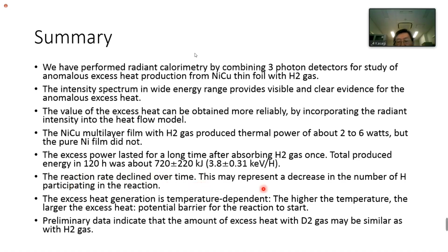This may represent a decrease in the number of hydrogen atoms participating in the reaction. The excess heat generation is temperature dependent. The higher the temperature, the larger the excess heat, suggesting a potential barrier for the reaction to start. The preliminary data indicate that the amount of excess heat with D2 gas may be similar to that with H2 gas.